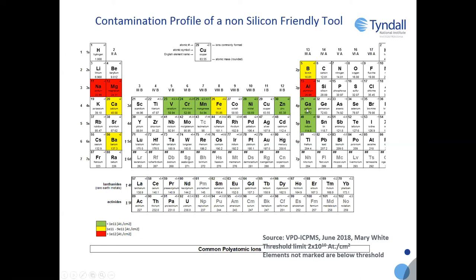Aluminium is not an issue because we sputter aluminium onto our silicon devices, but we don't want aluminium in layers where there should be no aluminium because it's also a P-type dopant. Similarly, if we ended up putting a wafer in here, getting it contaminated with gallium and it going back into a silicon-friendly tool, we'd be introducing P-type dopant in an uncontrolled fashion. So I suppose the segregation between the different labs and between the different tools is very much driven by getting the best devices possible for all of our customers.